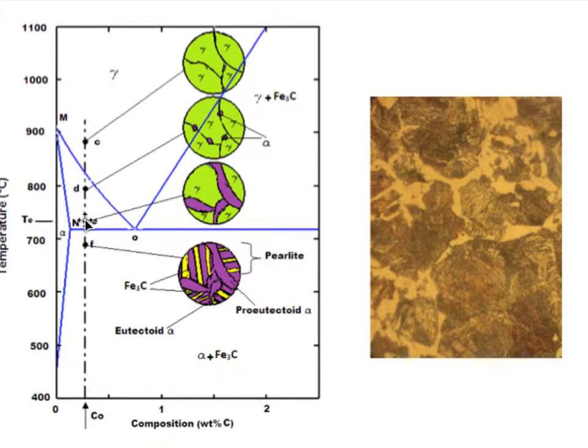And we can also see what the pearlite consists of: ferrite and cementite, which we have the composition far away here. And we can see maybe the thin cementite lines here, the plates of cementite are very thin compared to the ferrite, as we are positioned here rather closely to the ferrite in this two-phase region. So we end up here with a structure with pearlite and proeutectoid ferrite in the original austenite grain boundaries.